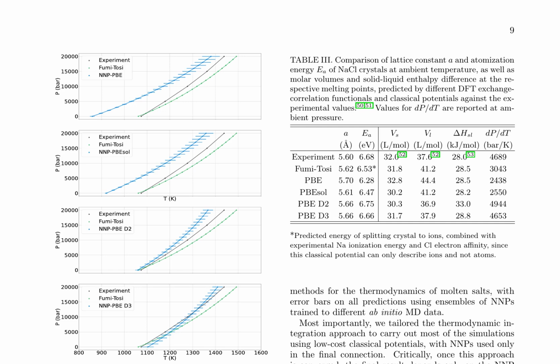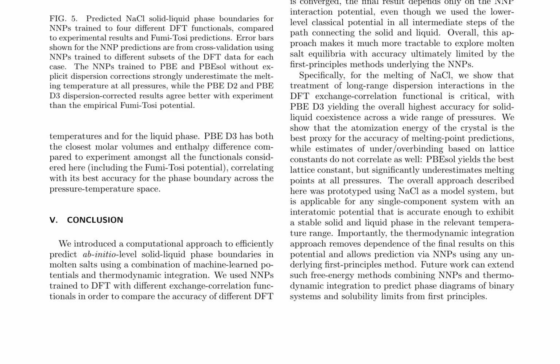Here is the combined summary of pages 9 and 10. This research presents a novel computational approach for predicting solid-liquid phase boundaries of molten salts using machine-learned potentials and thermodynamic integration. Focusing on sodium chloride as a model system, the method demonstrates its potential for predicting phase diagrams in single-component systems. The study highlights the importance of long-range dispersion interactions in DFT exchange correlation functionals, with PBED3 showing the highest accuracy among the functionals considered.